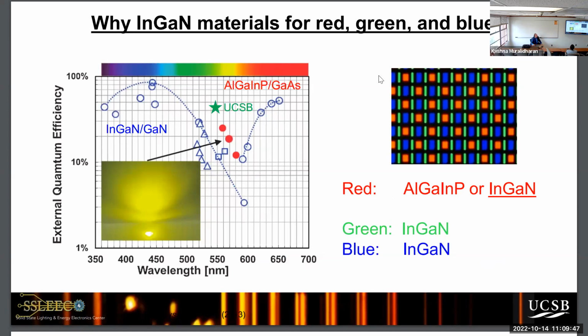So let's go back a little bit to the material science and talk about why this display will start to revolutionize, particularly mobile displays. And we look at something called quantum efficiency. So 100% quantum efficiency means you get 1 photon for 1 electron you put in. So the absolute best you could ever get is 100%. So you can see the gallium nitride material system, we're already almost 90% efficient. That means if I put in 1 watt of power, I'm gonna get out 0.9 watts of optical power. So this has led to the revolution in lighting.